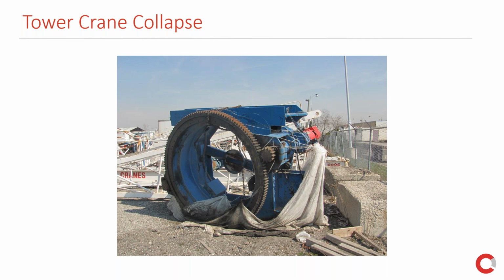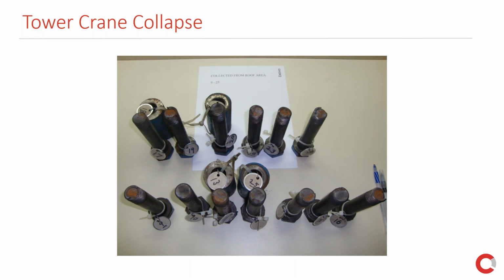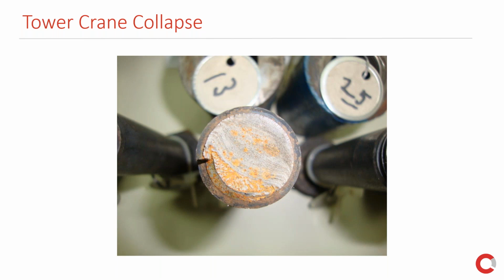The incident occurred because a component called the slew ring failed. The slew ring allows the crane to rotate 360 degrees, and it's held in place by 48 bolts. We couldn't find all the 48 bolts, but we found a few relevant ones, and they were taken to a lab for examination. And following examination by naked eye and under a stereo microscope, we determined that the bolts failed as the result of fatigue failure.